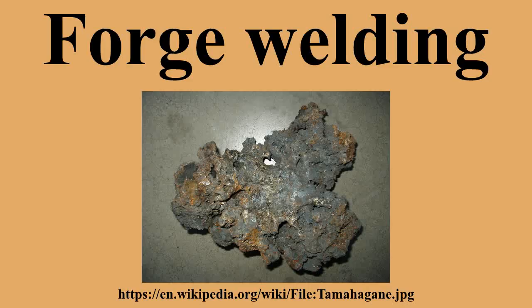Copper and its alloys are usually better joined with cold welding, explosion welding, or other pressure welding techniques. With iron or steel, the presence of even small amounts of copper severely reduces the alloy's ability to forge weld. Titanium alloys are commonly forge welded. Because of titanium's tendency to absorb oxygen when molten, the solid-state diffusion bond of a forge weld is often stronger than a fusion weld in which the metal is liquefied.